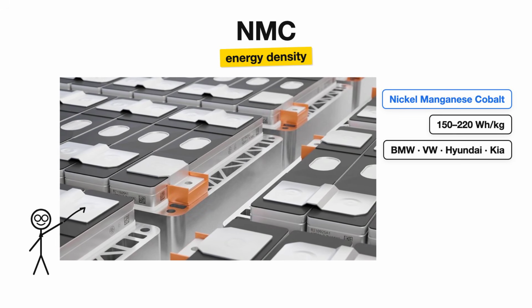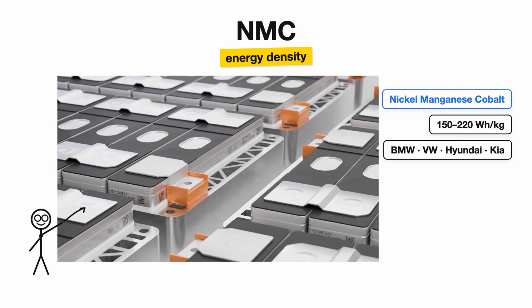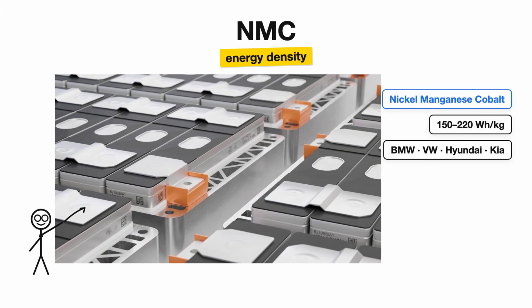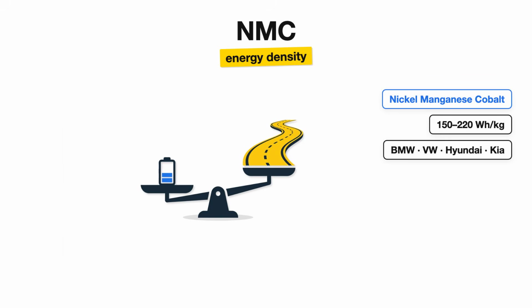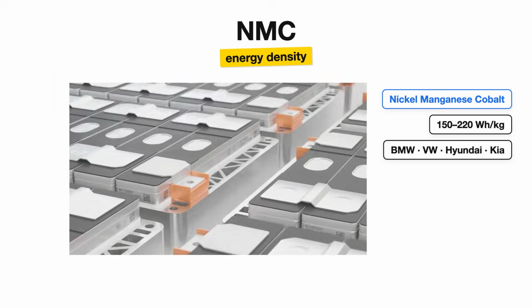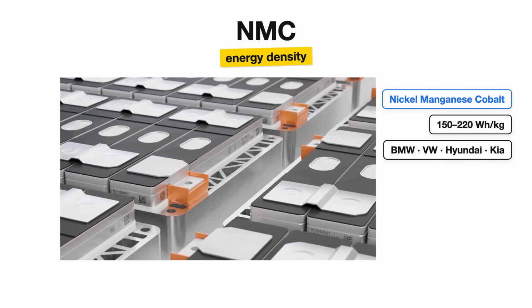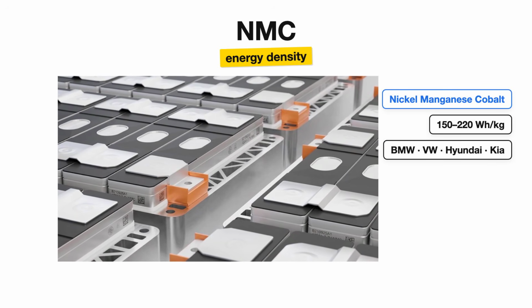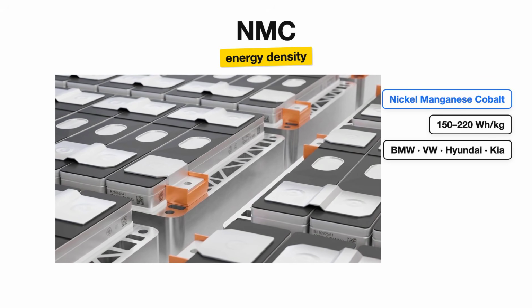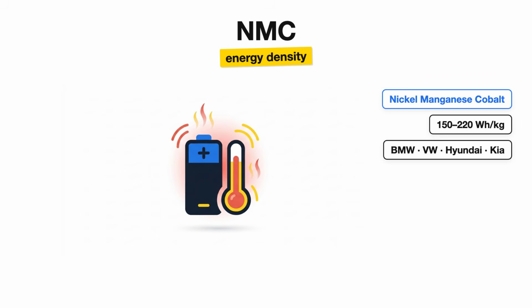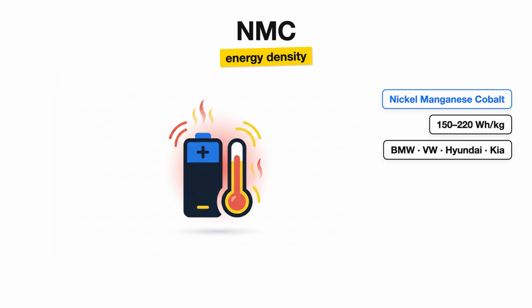That stands for nickel manganese cobalt, and it is what most Western EVs run today. BMW, Volkswagen, Hyundai, Kia. If you are driving a non-Tesla EV in America, there is a good chance it has NMC chemistry inside. The reason is energy density. NMC can store between 150 and 220 watt-hours per kilogram of battery weight, which means more range for a lighter pack. That matters a lot when you are trying to get 300 miles out of a mid-size SUV.